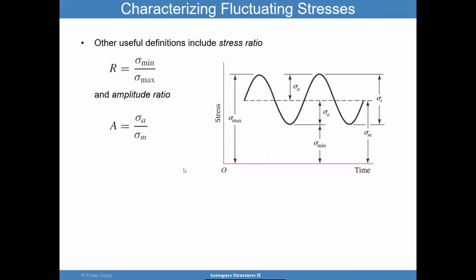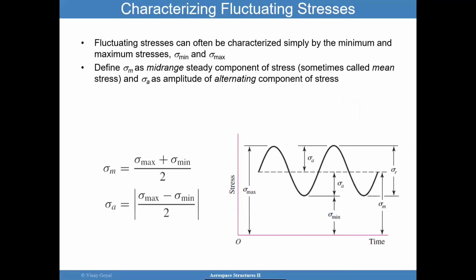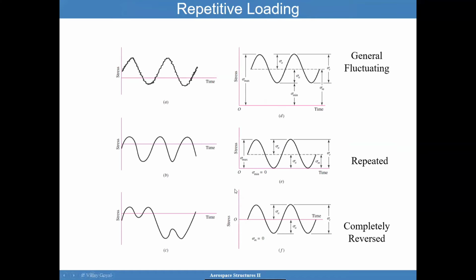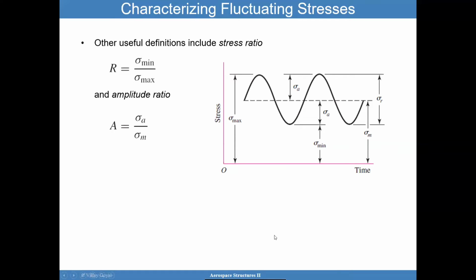So the stress ratio tends to be very important because that tells me if I have a reversible type situation. If R equals -1, then sigma min is the negative of sigma max, and so I have a fully reversible cycle. Let's look at this again here. Sigma max is 300, sigma min is -300. 300 divided by -300 is -1. And as you can see, R of -1 becomes a stress ratio that gives me a fully reversed situation.